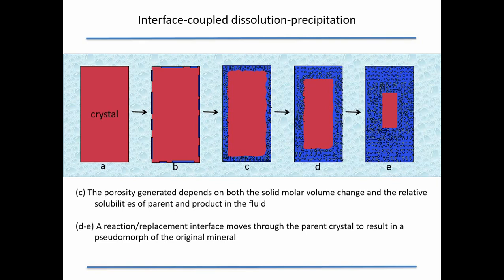So this is what we called interface-coupled dissolution precipitation, because it's all happening at that very, very fine level at the interface. It will be different thicknesses of an interfacial fluid depending on the situation, but we're initiating it with initial dissolution. So we're talking about almost a sub-nanoscale level is where the reaction begins. And once the reaction can begin, it tends to keep going. And although we're relying on molar volume changes between parent and product and on reactivity or solubility differences, we see these kinds of reactions happening all the time.